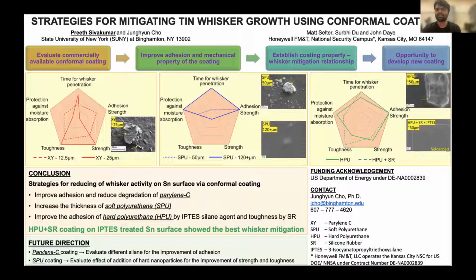Based on the results which we saw, first, when there is a conformal coating, the number of whisker activities on the tin surface reduced drastically. That was because the moisture reaching the tin surface is delayed, which means there is less stress in the tin layer, which means delayed whisker formation. Within the conformal coatings, for parylene, an increase in the thickness reduced the adhesion strength, which had a huge impact on the whisker activity. The reduction in adhesion strength for thicker parylene coating led to whisker formation at an earlier stage and penetration at a slightly later stage.